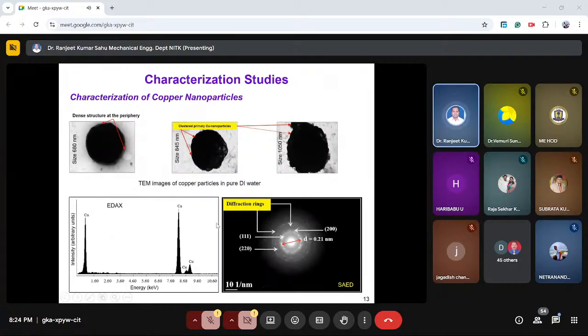Then after that, what happened? From this EDX and SAED pattern, it has been verified that the copper particles obtained are purely crystalline in nature, and no impurities are present in the sample. But it has been observed that the particles obtained are of submicron size rather than nano size. Even though ultrasonic vibration was provided to avoid agglomeration of debris, large particles were still obtained. This indicates that the ultrasonication was not very effective in preventing agglomeration.